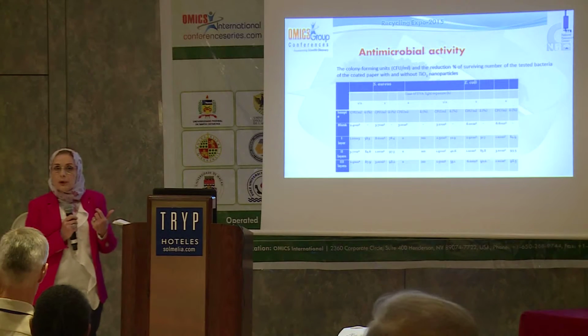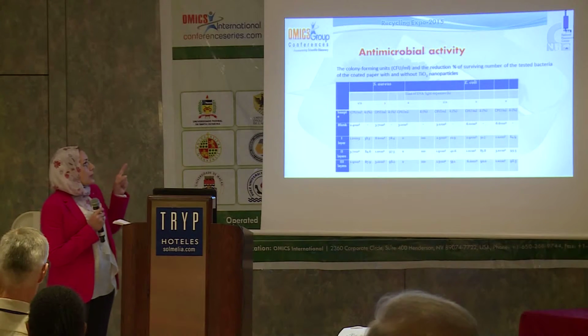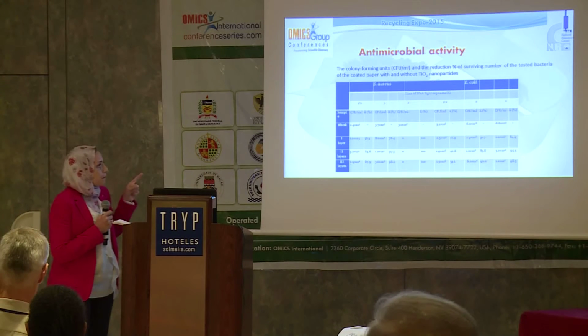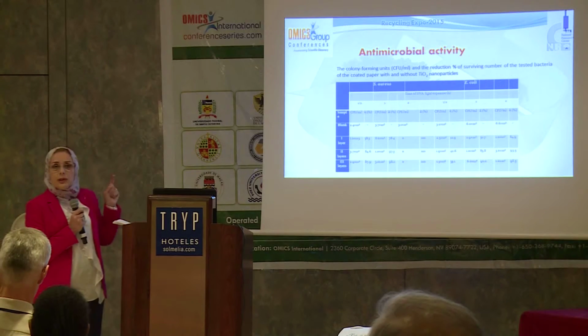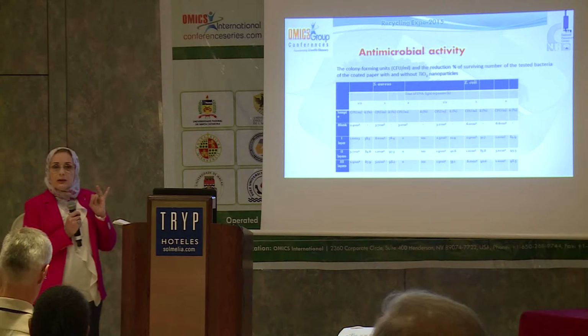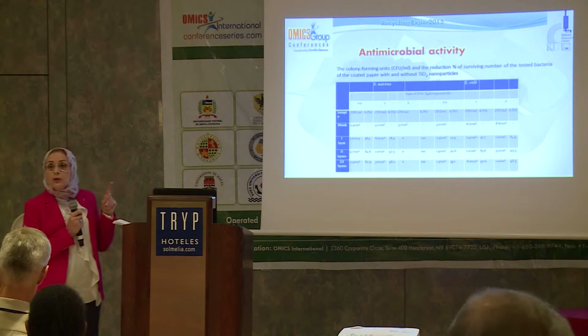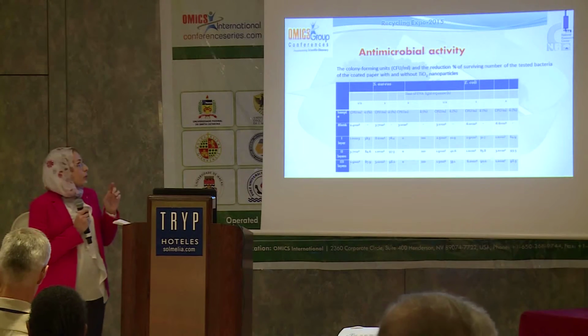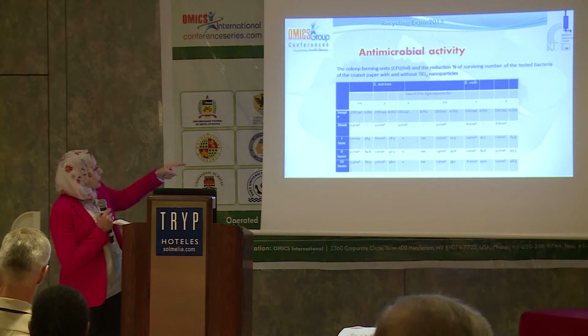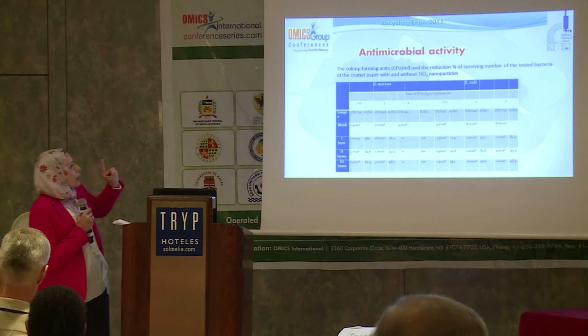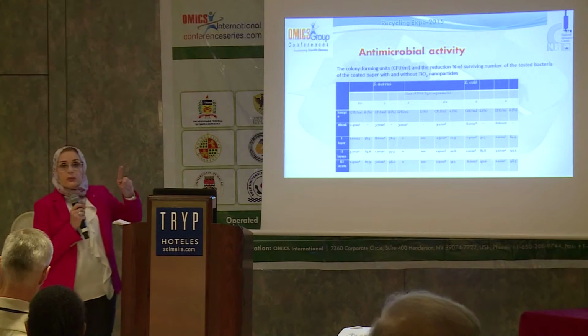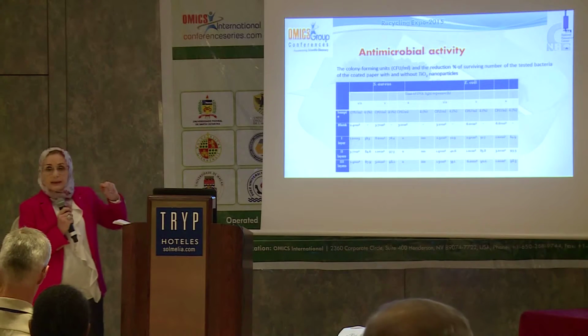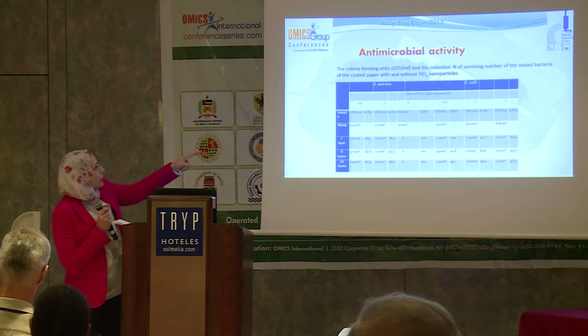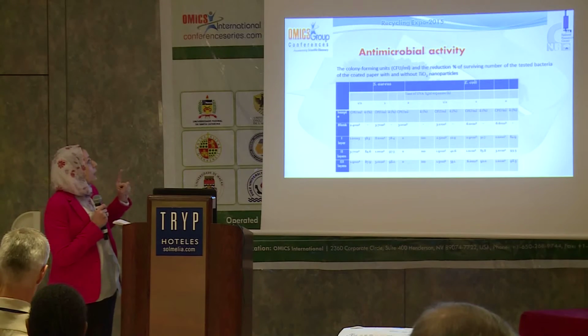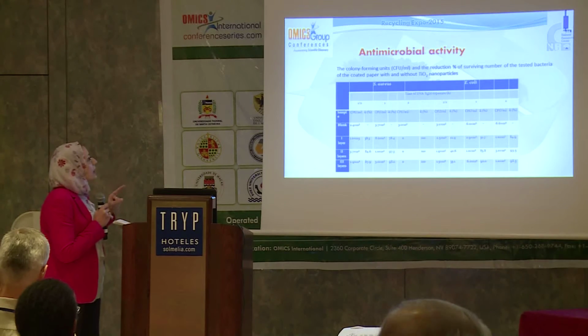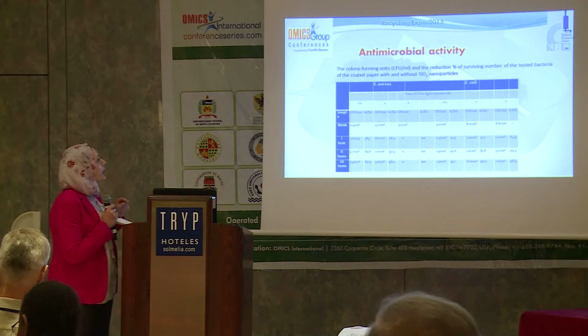We chose the last solution, consisting of wheat gluten, cellulose nanocrystals, and titanium dioxide, to coat commercial paper with 1 layer, 2 layers, and 3 layers. The coated paper was exposed to UV light for half an hour, 1 hour, and 2 hours. And this table shows the colony forming units and the reduction percent of the surviving number of the